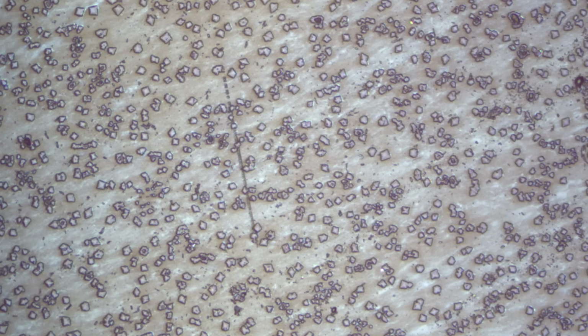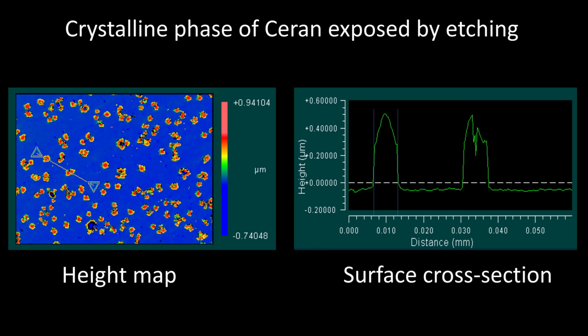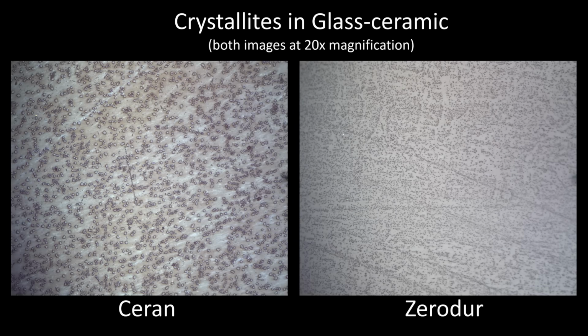Here I plotted a height map of the etched surface, illustrating the size of the crystals and the height that they stick out of the rest of the surface. In this case, the 2 crystals shown in the plot are about 6 to 7 microns wide and stick up around 0.6 microns. I also performed the same procedure with Zerodur, and here the crystals are definitely much smaller. These 2 images have the same scale, and I estimate the crystals in Zerodur to be around 1 micron in size.